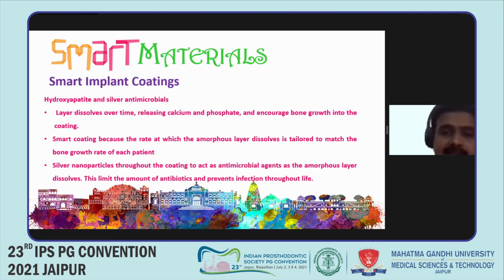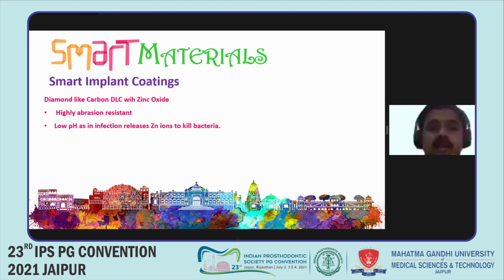The same is what we also see with respect to DLC and zinc oxide, which is a very abrasion resistant material, and at the same time is also kind enough that in response to a decrease in the pH, we get a release of zinc ions, or in the earlier case, the silver ions, which are lethal to the bacteria. So because of this, they have been seeing to it, because we do see that the moment we see that